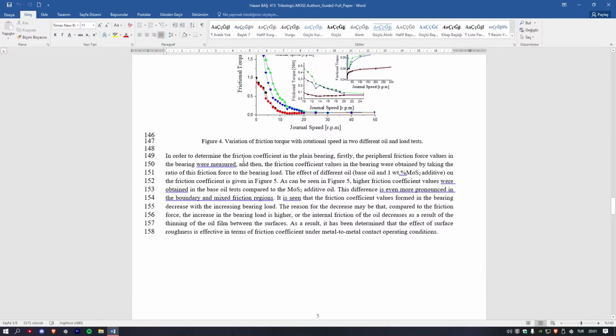In order to determine the friction coefficient in the plain bearing, firstly the peripheral friction force values in the bearing were measured, and then the friction coefficient values in the bearing were obtained by taking the ratio of this friction force to the bearing load. The effect of different oil on the friction coefficient is given in figure 5. As can be seen in figure 5, higher friction coefficient values were obtained in the base oil test compared to the molybdenum disulfide additive oil. This difference is even more pronounced in the boundary and mixed lubrication regions.